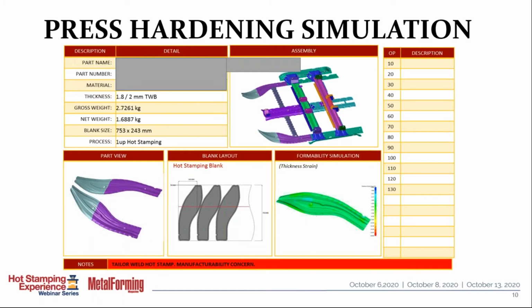Not only do we have to do a simulation that validates the potential of making the part properly and forming it properly without splits or wrinkles or excessive thinning or residual stress, we also have to simulate the heat treating process. And we have to do those both at the same time. So these are a lot more complex to set up and operate, but they have been developed and the process is relatively mature.